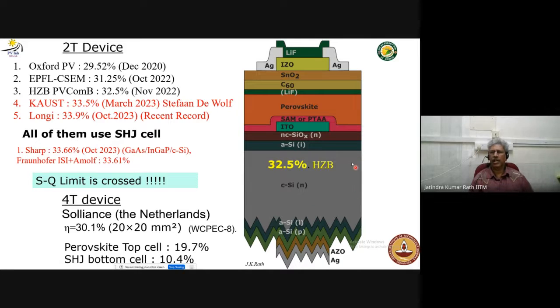This is the silicon heterojunction cell with one side rough, the other side flat. Normally it should be textured, but they are flat because perovskites or any other polycrystalline material cannot grow on top of a textured surface. So it has to be flat, and maybe a minor texture will be there. But you can see a lot of various types of materials have to be grown to make it work.